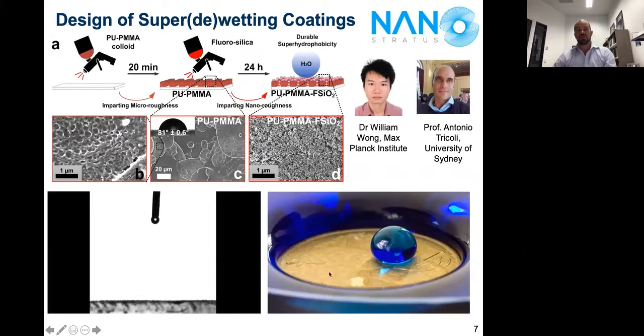And what you can see here, this is an Australian dollar coin, where you can see the kangaroo and his ears here. And what we did is we coated this coin with this technology, and you can see that it's transparent. And we've just dyed the water blue, and you can see this is the student William here, his reflection in the droplet. But what you can see here is the wall of water around the outsides of the coin. So it's actually parting the water. It's called the Moses effect. The surface energies are so great that it's actually holding the water back off the surface of this coin, which really demonstrates the technology really well.